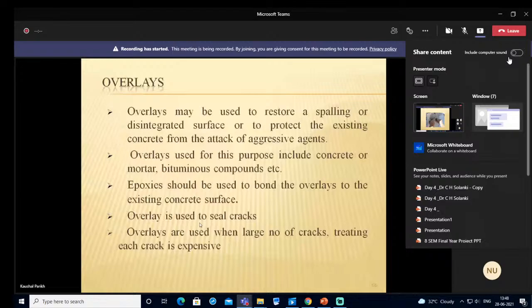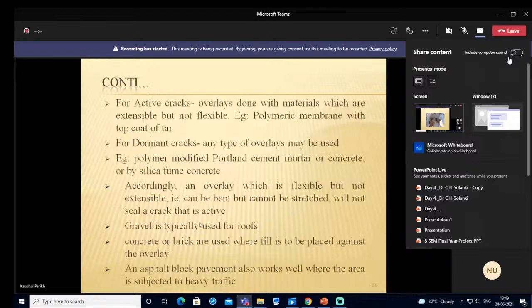Overlay is used to seal cracks. Overlays are also used when a large number of cracks are there, because fixing each crack is expensive. For active cracks, overlays are done with materials which are extensible but not flexible, like polymeric membrane with a top coat of tar. For the inactive cracks, any type of overlay may be used, like polymer modified cement mortar or concrete or silica fume concrete. An overlay which is flexible but not extensible can bend but cannot be stretched, so it will not seal a crack that is active.